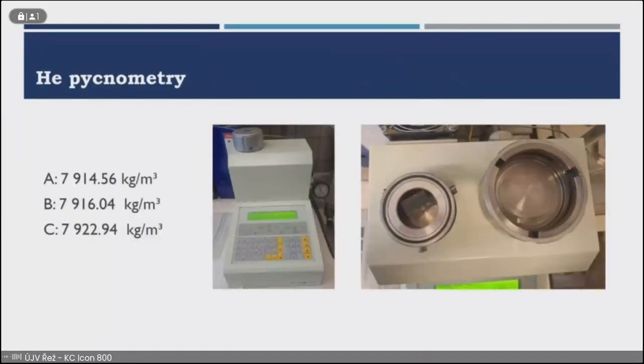Now I will talk about helium pycnometry. Helium pycnometry is also a non-destructive method of testing. The first step of this experiment is necessary to find out the weight of the sample. In the second step, the sample is put into a container, and molecules of helium are streamed into this container. Then when the pressure in the container hits some specific value, the machine will automatically report a value of density. As you can see on this slide, the highest value of density was for sample C.